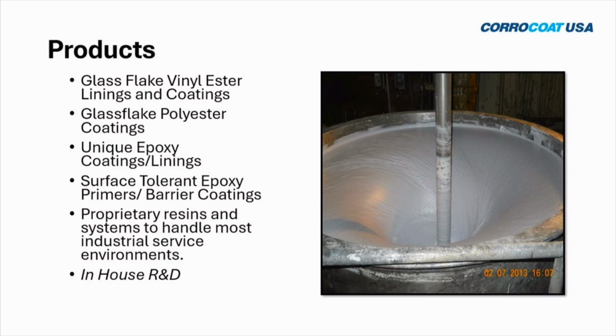So Corrocoat, we operate naturally on the Pareto principle. I'd say about 80% of our specs end up being glass-flake vinyl ester. That's when we're looking at internal linings. The vinyl ester resin, particularly Novolac vinyl ester resins, have an extreme temperature resistance and chemical resistance. That stated, we also make polyester-based resin coatings, also glass-flake reinforced, a variety of different types of epoxy resin-based coatings, specialty coatings, and surface-tolerant primers to where maybe blasting isn't feasible. So we can do a lot of things with our technology and experience.